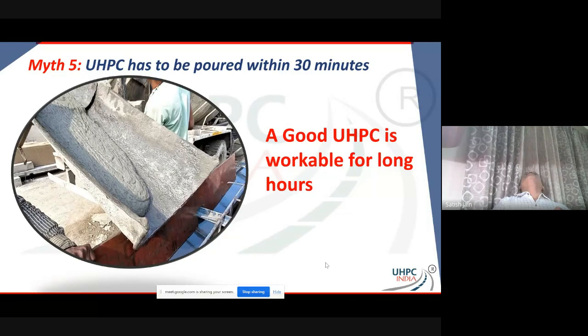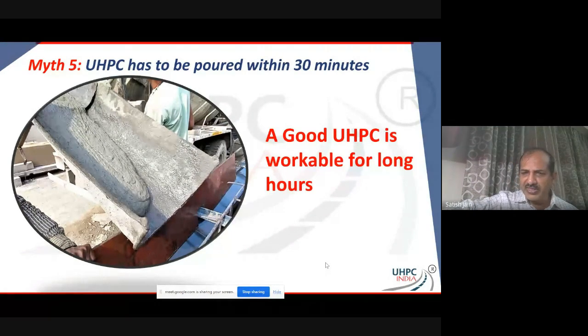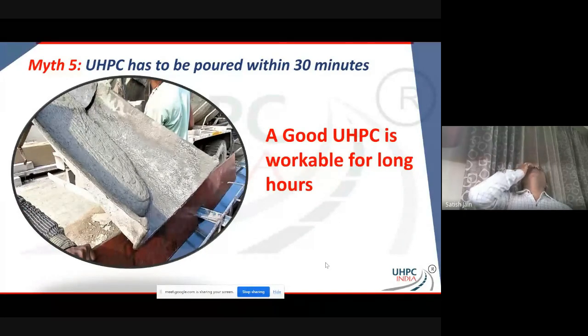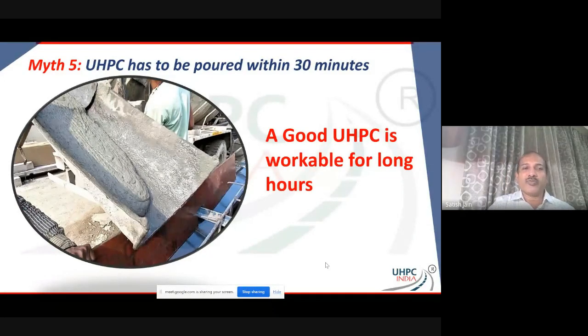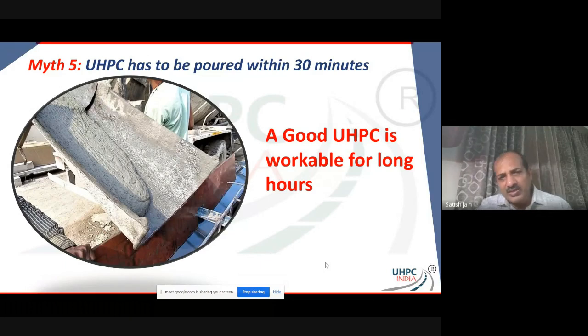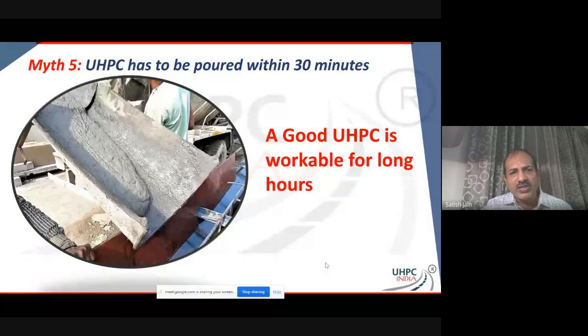And so for UHPC, you just need what? You need retention admixtures, right? You can retain your UHPC as long as you want, 2 hours, 4 hours, 6 hours. It's up to you, depending on what you're devising. So all that's possible, all that's really possible. So these kinds of myths or misinformation that's spread around, one has to understand that at the end of the day, it is a material. Yes, the quality control has to be high, but it is still a material which you can play with and you can create your own, right?